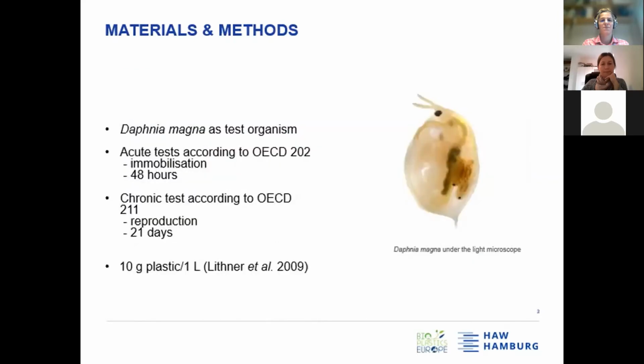So first I would like to start with the materials and methods we used for the daphnid testing. Daphnia magna was used as test organism, and here on the right side you can see a daphnid under the light microscope with a magnification of 200. We performed 2 different types of tests. We performed acute toxicity tests according to OECD guideline 202. These tests last 48 hours, and the immobilization of the daphnids was observed.